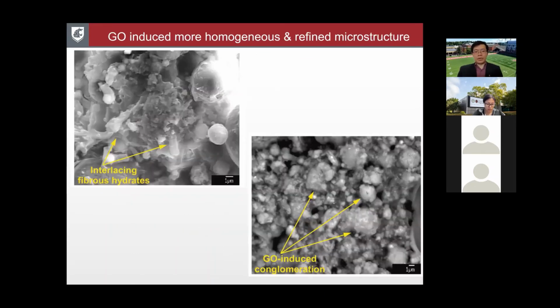Now, also we're seeing a refined structure. On the left-hand side, again, is the geopolymer without graphene oxide. This is after 5 rapid cycles of freeze-thaw in the presence of 3% sodium chloride. On the right-hand side is the one with graphene oxide. You can see that it's less heterogeneous. I wouldn't call it homogeneous, but less heterogeneous and less porous. The pores are much finer.